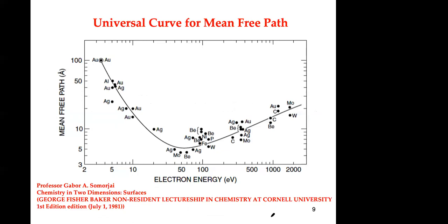This is called the universal curve, and it comes up now and then. It's basically an indication of the distance, the mean free path, usually expressed as lambda. It's how far an electron can move inside a solid without losing kinetic energy. Here, obviously, they have different metals and they're plotting the depth the electron can move without losing energy. So usually in XPS, you work in this region.